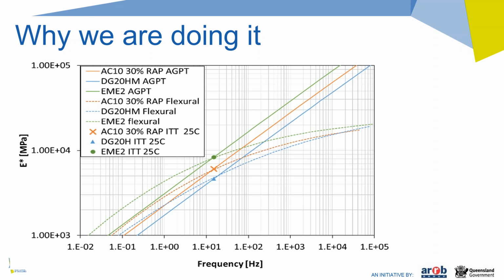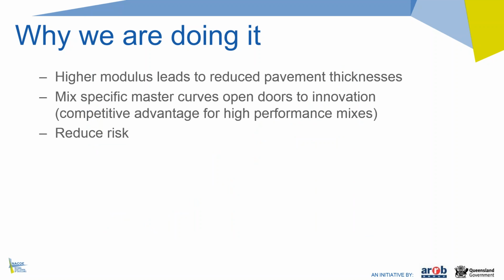The actual measured flexural modulus, the flexural modulus that we've measured in the laboratory, is also shown on the graph. Those are the dashed lines. And as you can see, on the left of the graph, that is the high temperature and low load frequency domain, the modulus values that we get from the actual measured flexural modulus are higher than what's currently predicted in Austroads. And that in turn, of course, will result in thinner pavements when we're using those more realistic values.